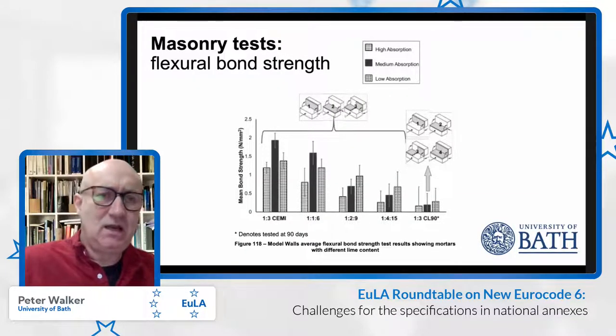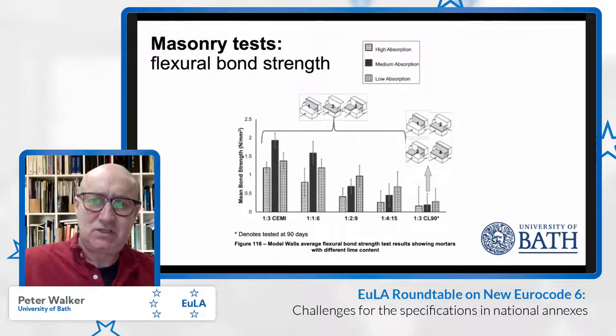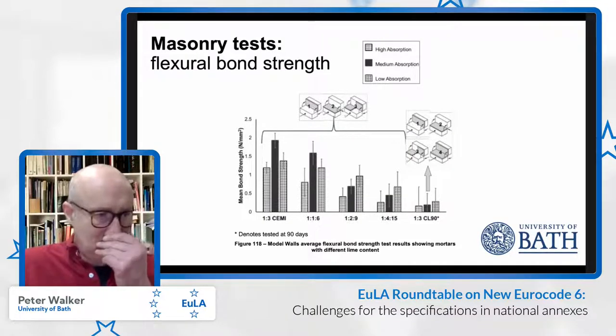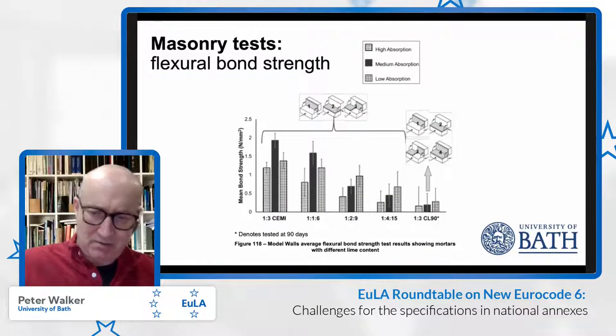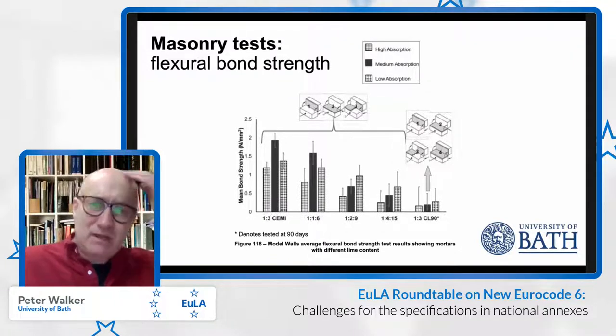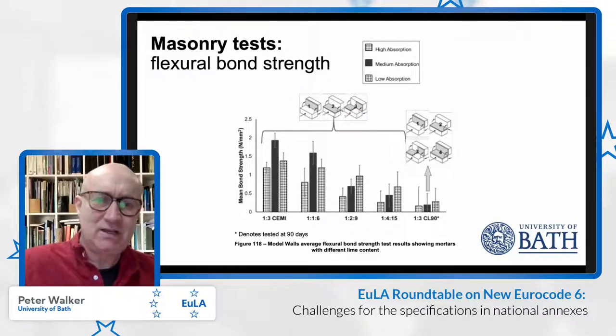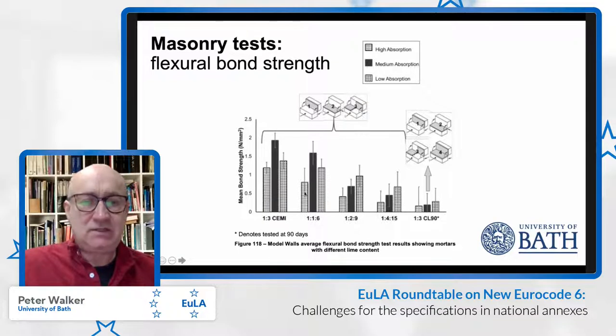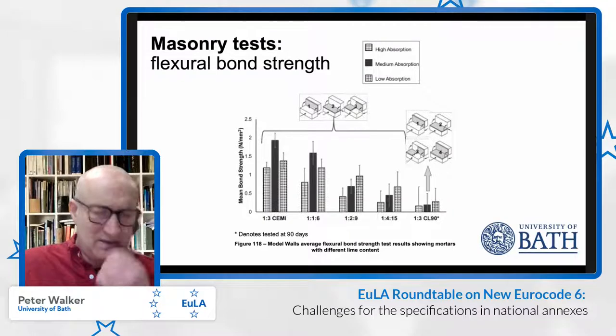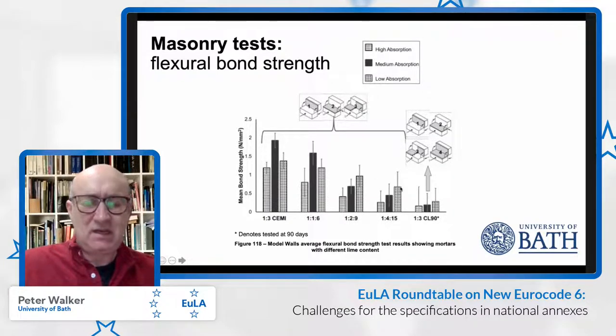Not to dwell upon this, but we also did a lot of testing on flexural bond strength. In this case, we just used the bond wrench test. So we didn't look at the orthogonal flexural strength properties by measuring parallel and perpendicular to the bed joint. We just did perpendicular to the bed joint, where the plane of failure is parallel to the bed joint, the weakest direction, using the bond wrench test. Here you can see the flexural bond values and the influence of the mortar content on those bond strengths. Again, similar to the compressive strength of the masonry, the flexural bond strength does not decrease at the same rate in keeping with the change in mortar strength.